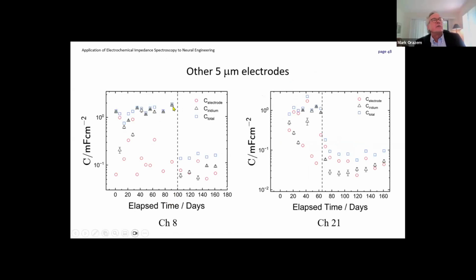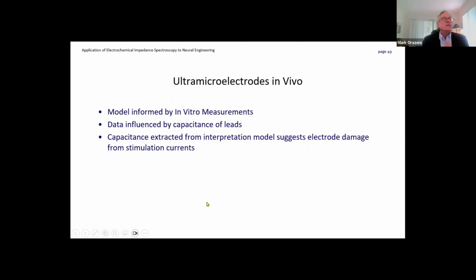If we looked at other 5 micron electrodes, what we see is that this behavior is always the same. It works well around 1-2 millifarads per centimeter squared, and then drops by an order of magnitude. The duration, the time it takes to do that, changes, which is probably due partly to the history of the electrode, how many stimulations it has received, and also perhaps variations in the fabrication of the electrodes. So my point here is that the model was informed by in vitro measurements. The data was influenced by the capacitance of the leads, and the capacitance we extracted suggests electrode damage from stimulation currents.